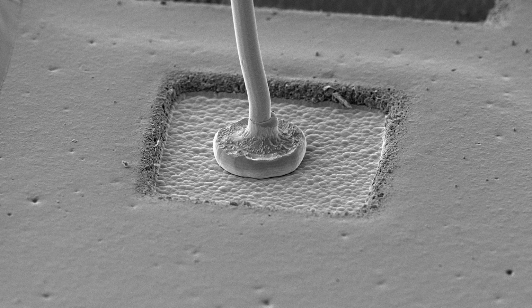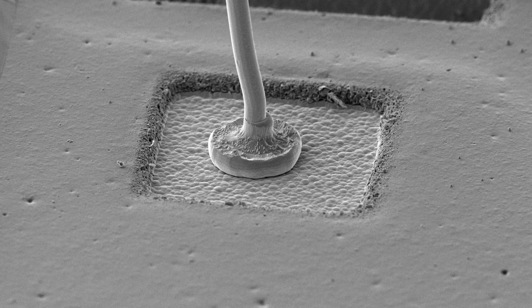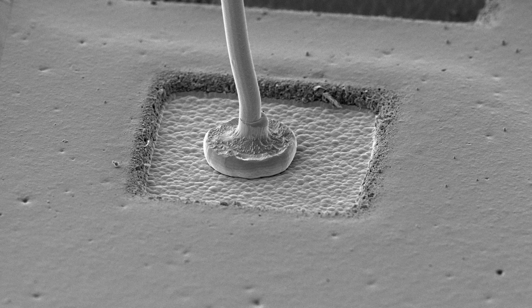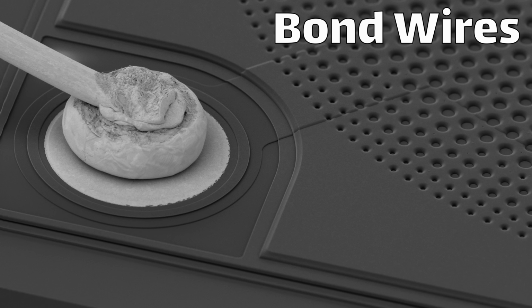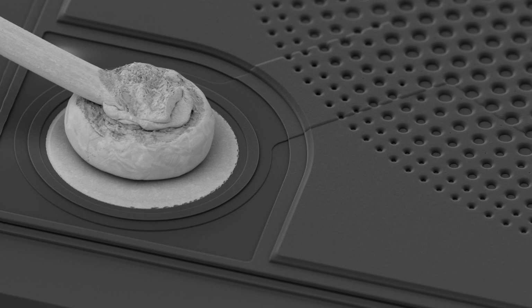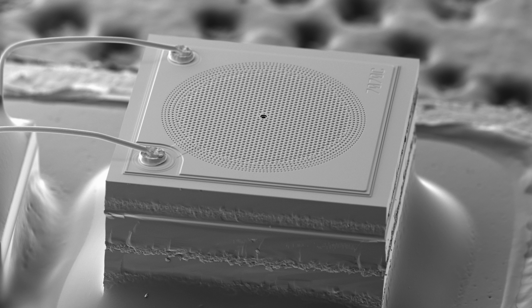I'm going to stop for a moment and take a closer look at those electrical connections because I think it's a really neat process. These are called bond wires, and they're formed from a very thin gold wire. The gold is melted at the end to form a ball, and then it's smushed down onto the device.